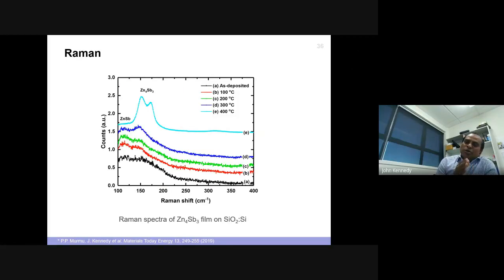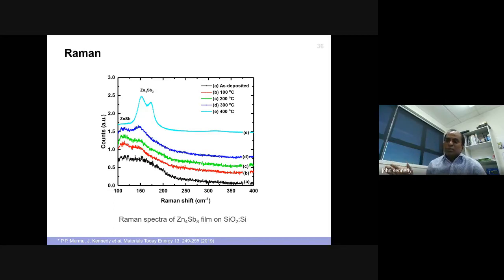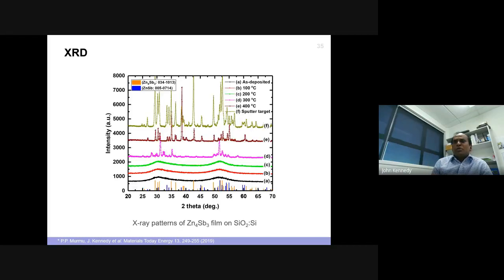Zinc antimony is well known for medium temperature, with high efficiency somewhere between 200 degrees and 300 degrees Celsius. Bismuth antimony telluride and bismuth telluride are quite good from room temperature up to 100 or 200 degrees. Then if you go to the next temperature range, 200 to 400, that's where zinc antimony comes in. And you can see in this Raman spectroscopy, even the previous one, at 400 degree anneal you get a beautiful crystalline zinc antimony as well.